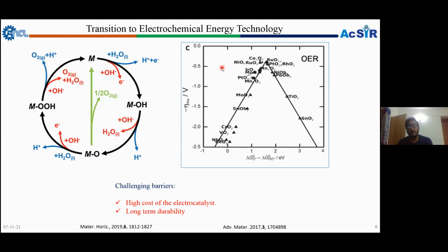Theoretical studies and a few experimental studies suggest that the most active catalysts for the oxygen evolution reaction are ruthenium oxide and iridium oxide, which have the optimum binding energy with the metal and other intermediates, giving the best activity. But the challenging barrier for these devices is that ruthenium and iridium are noble metal systems, so the electrocatalyst cost is high, and secondly there is the issue of long-term durability.